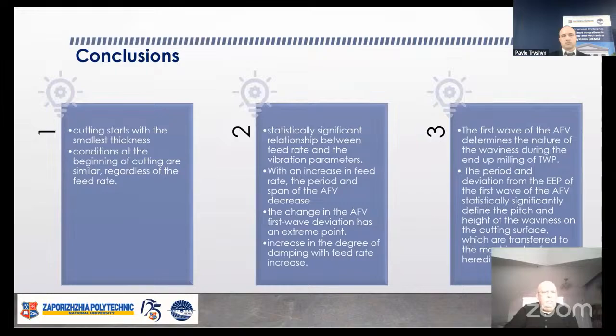And finally, conclusions. Cutting starts with the smallest thickness. Conditions at the beginning of cutting are similar regardless of the feed rate. Statistically significant relationship between feed rate and the vibration parameters were established. With an increase in feed rate, the period and span of the AFV decreases. The change in the AFV first wave deviation has an extreme point. Increase in the degree of damping with feed rate increase.